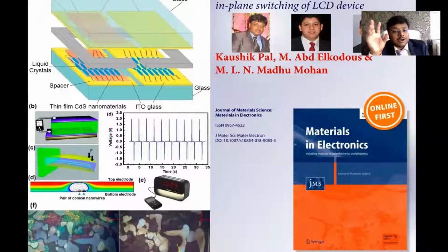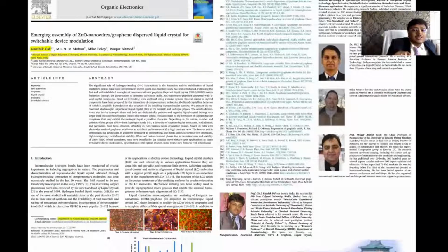And this is actually our liquid crystal device, which we made at laboratory scale. It is very simple: ITO-coated glass substrates we just sandwiched, and before that we make a thin film, and we properly aligned after grooving the liquid crystal and nanomaterials. Two electrodes come out, and you can see the on-state and off-state when it is placed under cross-polarizing optical microscopy. And the Journal of Material Science: Materials in Electronics just appreciated our work, and this is actually called our emerging self-assembly zinc oxide nanowires graphene dispersed liquid crystal for switchable device modulation technique we used here.